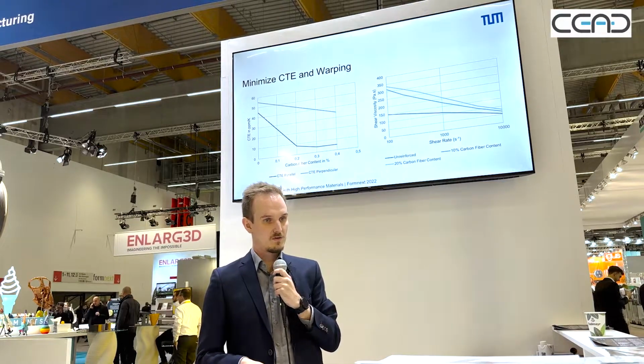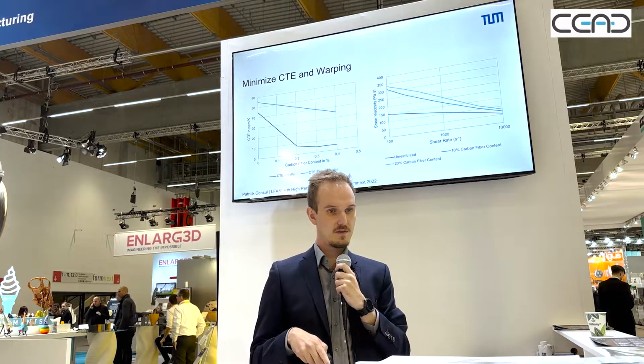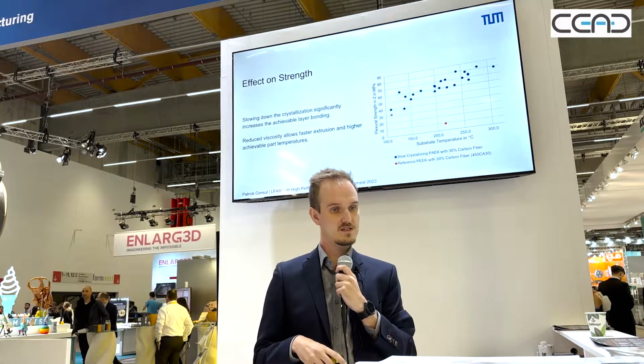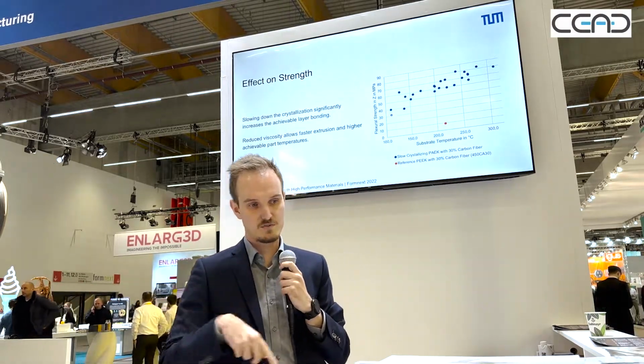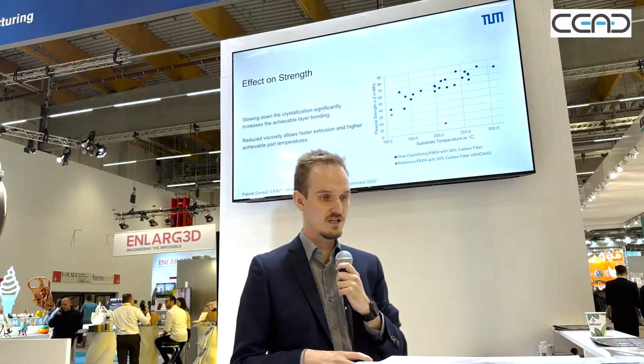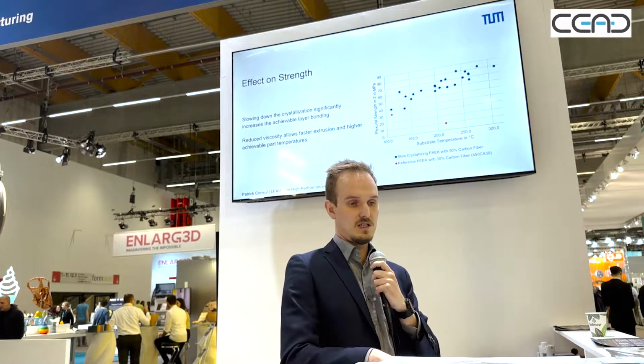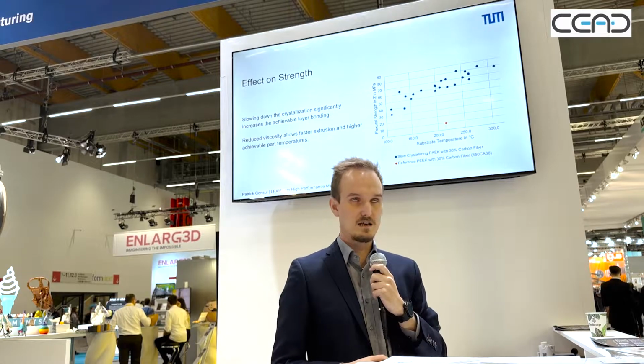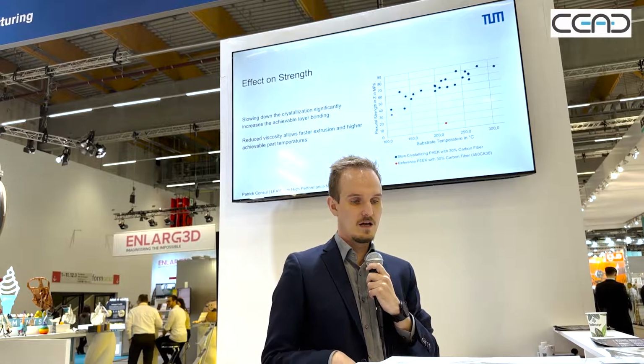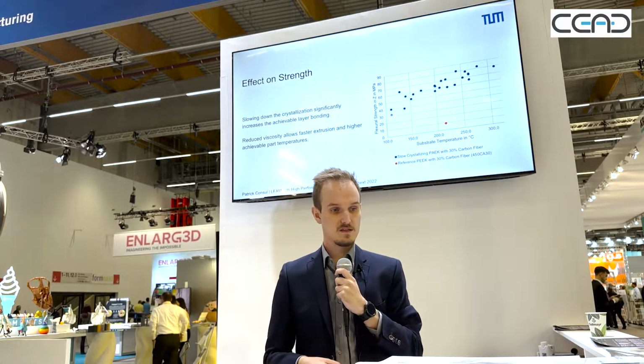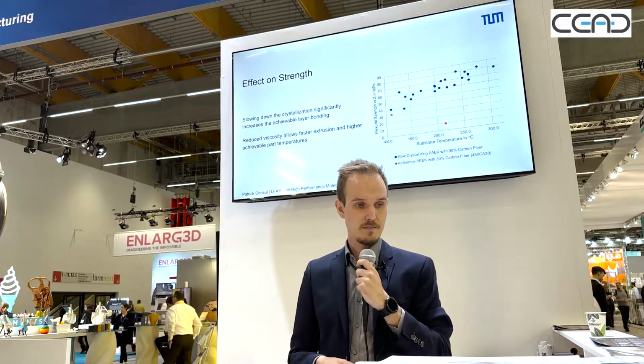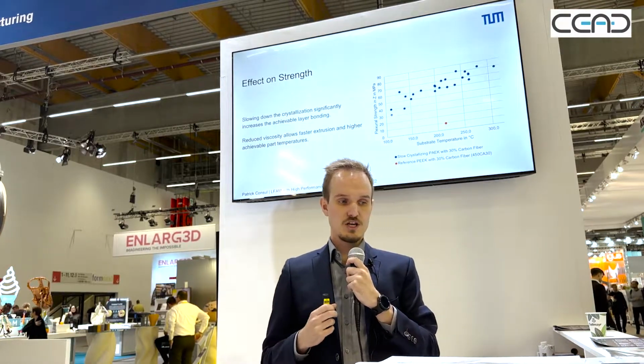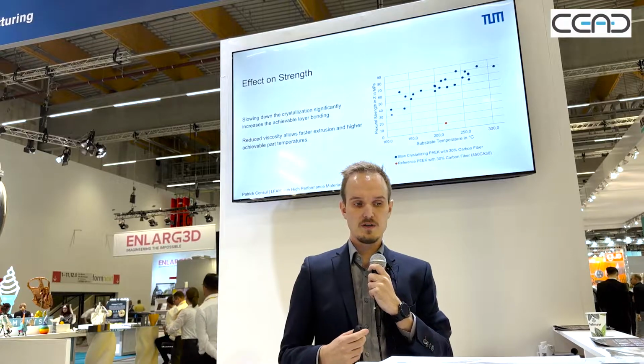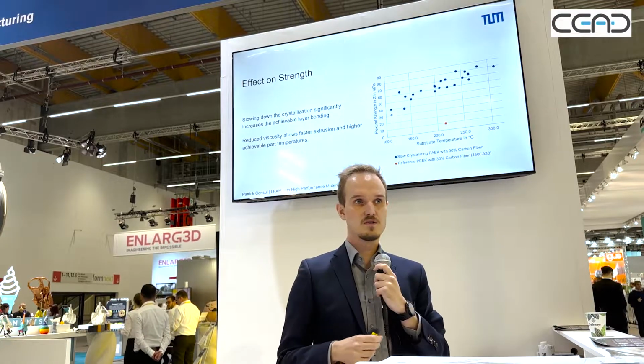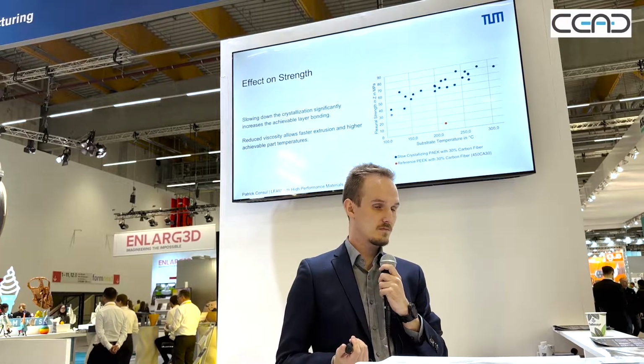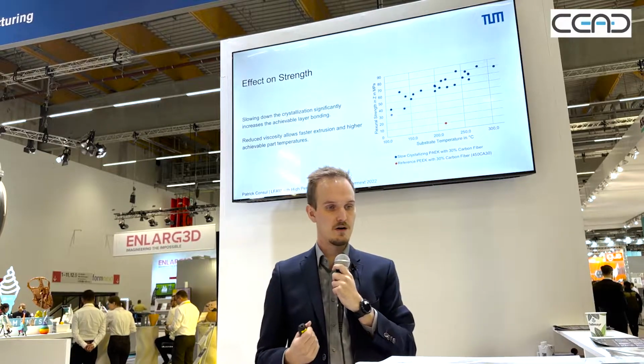And with those polymers, I ended up doing a couple of tests, printing cubes at different speeds and sizes to get different temperatures. I also printed a couple more cubes with a standard PAEK from injection molding. It's the little orange dot at the bottom. And with injection molding PAEK, the bonding you get is actually so bad that most samples break during preparation, which is why we only have one spot down there.